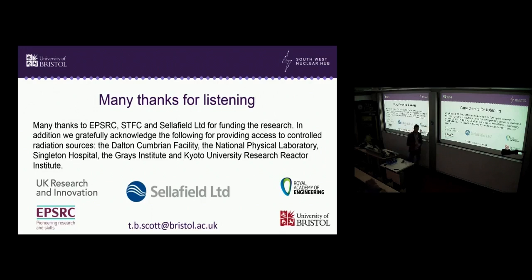So, great question. Your tritium beta particle, which is relatively low energy, its maximum range is about 200 nanometers. So it's tiny. For a beta particle, it gets up to about a micron. But I refer to these devices as surface area devices, because they are so thin. The actual thickness of the diamond is about 20 microns. And then you've got your metal terminations, and you'd repeat, just like the coin cell application.